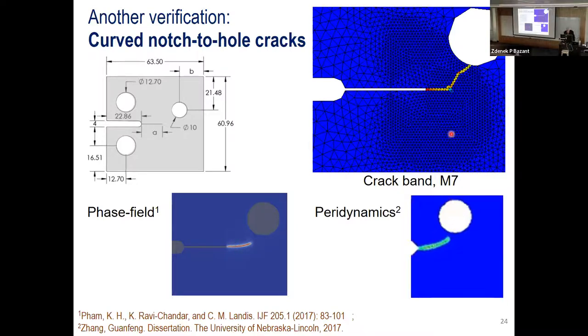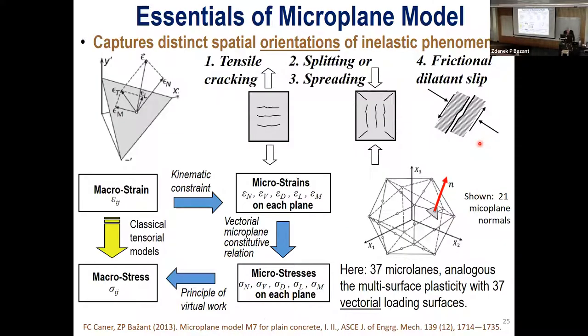Now the crack band model I show here. Crack band model would do a rugged crack, but it basically follows a correct result. A low deflection is indistinguishable. It's correct for practical purposes too, but not as smooth. Now I will use in the crack band model the microplane model. Let me say a few words.